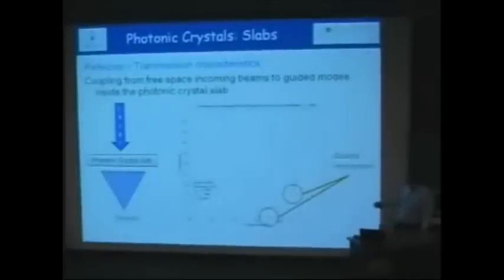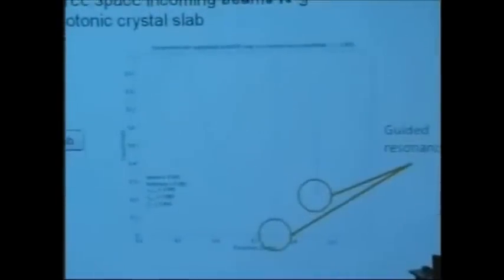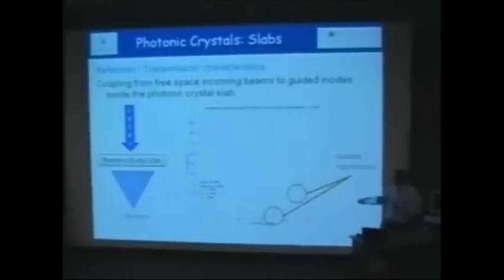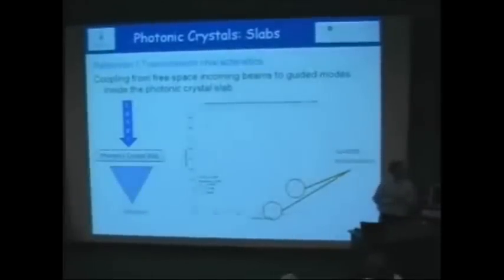So if you think about it, what we're trying to do is to measure the transmission versus wavelength. And this is a typical result we get from a simulation. As you could see over here, if you measure the transmission versus frequency, you get these guided resonances, these very sharp resonances in the spectra. The resonances come from the ability to couple light very efficiently into the waveguide. So these are examples of how very nicely I couple light in, and then they behave as guided resonances. Now, we could use these guided resonances for sensing, because what you could see is if you change the environment around the photonic crystal slab, these guided resonances would slightly move. So we have a high quality factor resonance, as you could see in these two examples. And not only did you have a high quality factor resonance, you also could use it for sensing. So this is what we're going to do.